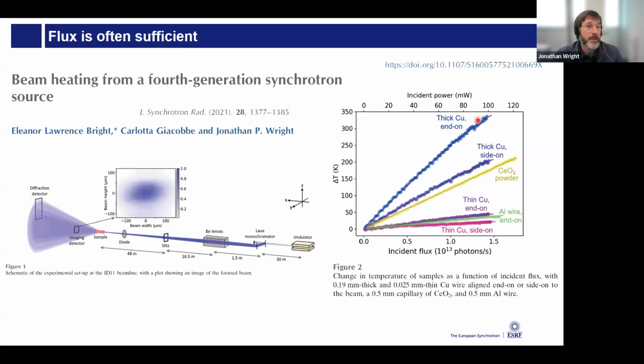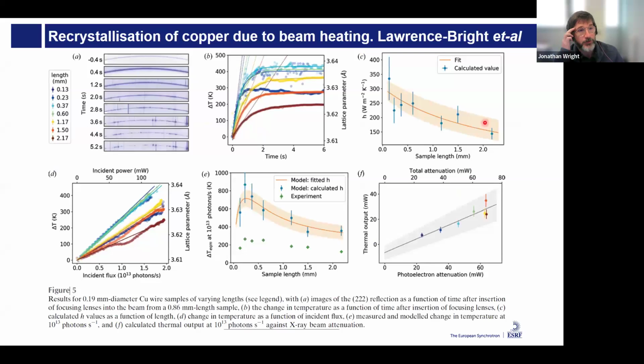And then the real proof of this, and this was quite stunning the day that it happened, was if you got the sample geometry just right and you stopped as many photons as possible and you thermally insulate the sample, then when you turn the beam on, you go from a fully deformed diffraction pattern to nice smooth diffraction rings, because the copper heats up sufficiently that it recrystallizes in the beam. So this is what happens when a plumber is welding the pipes in your house and you eventually get leaks because the copper's recrystallized. You can do the same thing with the X-ray beam.